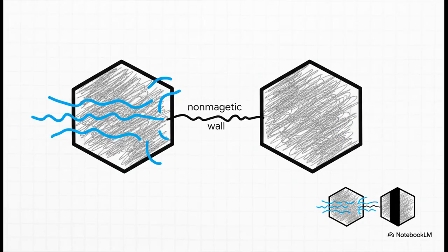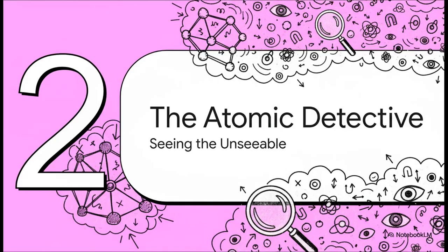Well, there was a huge problem with this theory. When they did the math, it showed that these non-magnetic walls would only be about 0.6 nanometers thick. We're talking the width of just 2 or 3 atoms. It's impossibly small. And other research had already proven that you needed a barrier at least twice that thick to actually stop the magnetic interference. So the theory sounded good, but the numbers just didn't add up. So the old theory was basically falling apart at the seams.